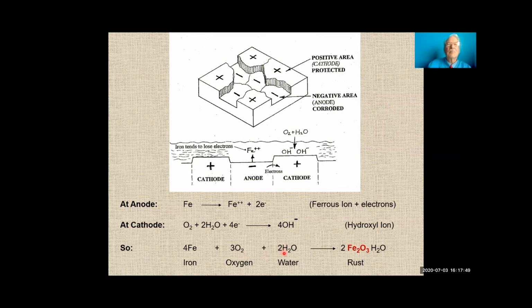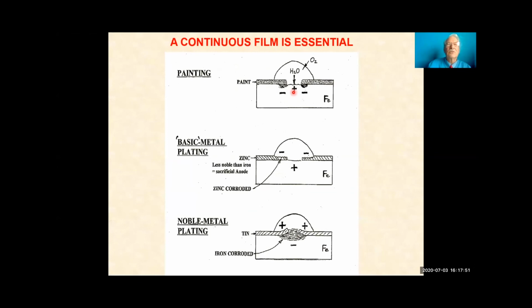But I just want to make the point again that the paint on the surface must be continuous, because if it's not, and you have a surface getting wet, remember the oxygen gets into the water, you end up with a hydroxyl ion, that generates a negative charge there, a positive charge, a negative charge there, and the corrosion will spread underneath the paint coating.